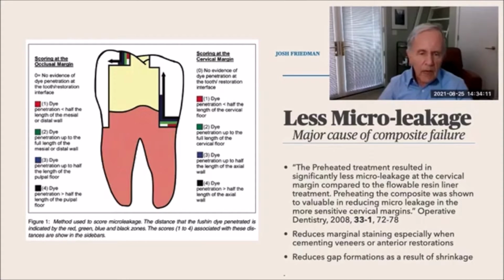Now, what they do in a dye study is they soak the material overnight in a red dye, and then they section the teeth and they look to see where the red is penetrating into the restoration. And what they found was pretty obvious, that the condition number 3, which used the preheated composite, had the least amount of leakage. Now, why is that?